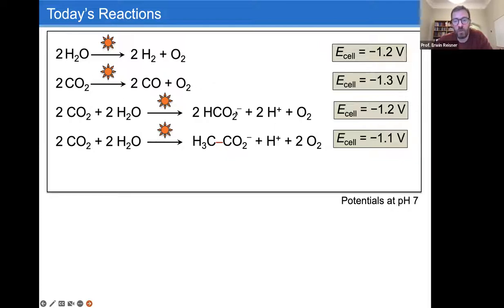If you reduce CO2 to formate, you can also couple this to oxidizing water to oxygen. And then I will also talk about C-C bond coupling by reducing CO2 to acetate and oxidizing water to oxygen. So these are all reactions with various difficulty. I would almost say we go from top to bottom in terms of difficulty. Maybe the middle two are similar. But importantly, with difficulty, I mean kinetic difficulty, because thermodynamically, they're all very similar.